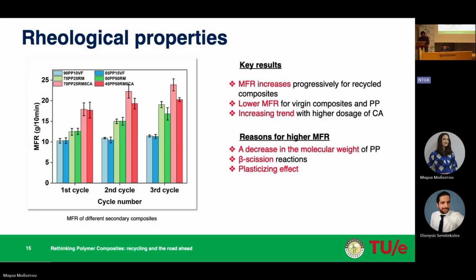rate. And also, there is another possibility where, due to the addition of coupling agent and a few other things, there might be a plasticizing effect, which will actually increase the melt flow rate of these composites. So since the recycled composites have better flowability, we can say that these composites are also favorable for injection molding. And yeah, there is a possible chance for these composites to be upscaled to an industrial level.